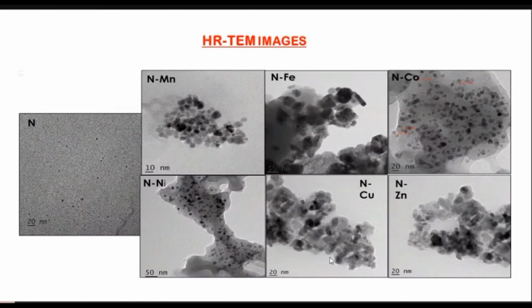The size and morphology were studied using TEM. This is what we have obtained. Here we can see that the nitrogen-doped carbon dots have a size less than 20 nanometer, while the co-doped carbon dots show a greater size. Also, they differ for different transition metals.